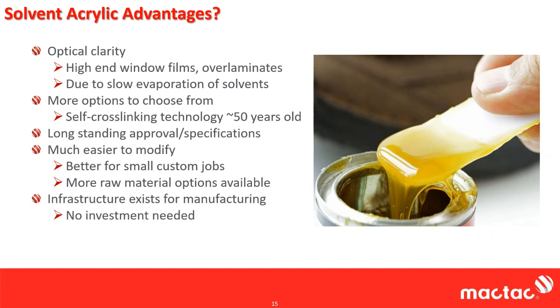With a solvent-based adhesive, you just need a simple air mixer, or just a simple drive shaft, like a Ross mixer, and you can stick it in a drum or you can stick it in a churn, and you can just throw in a bunch of additives, and they're going to dissolve and be dispersed very easily. That simply isn't the case per se with UV adhesives. Modifications can be done. They certainly can be tailored, but it's a lot harder to do just given the nature of them and the equipment that's needed.